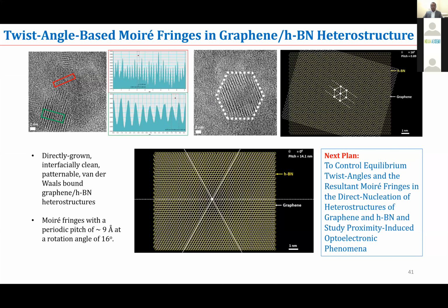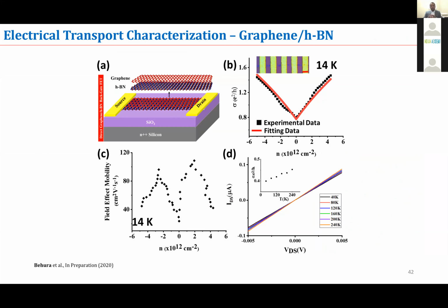using any rotation tools. And since these structures are interesting and directly formed, we were able to measure the electrical conductivity and found about 100 centimeter square per volt second electrical mobility, which is two orders of magnitude higher in comparison to the directly grown heterostructures that I've done so far, which showed only about 1 centimeter square per volt second.